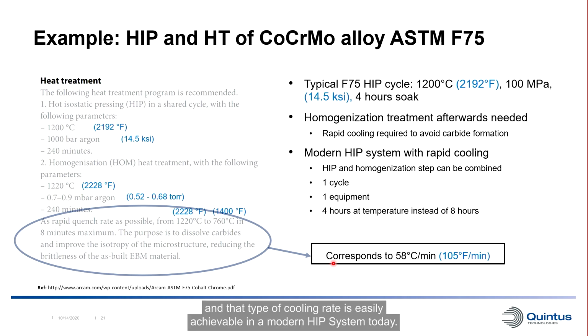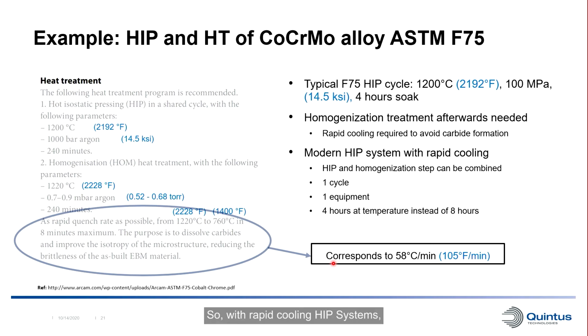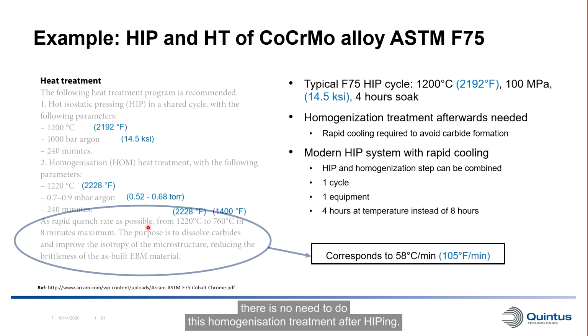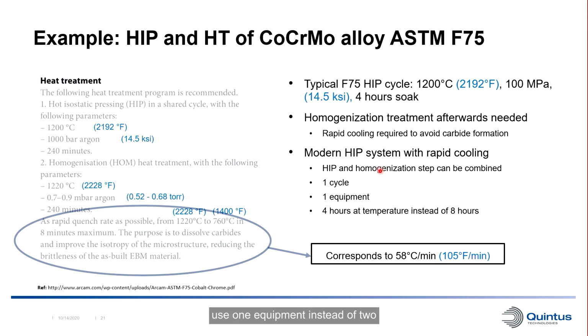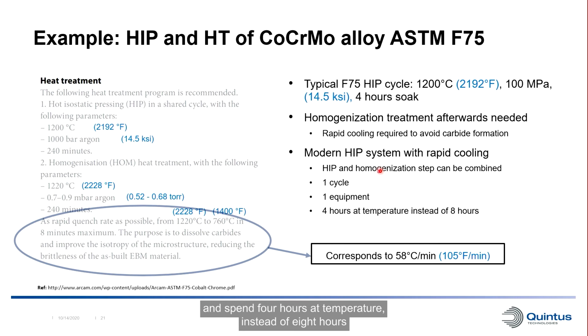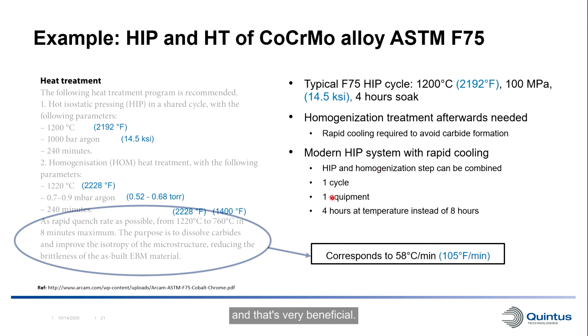And that type of cooling rate is easily achievable in a modern HIP system today. So with rapid cooling HIP systems, there's no need to do this homogenization treatment after HIPping. You can do the HIP step and then do the rapid cooling from here instead. So in that case, you would do 1 cycle instead of 2, use 1 equipment instead of 2, and spend 4 hours at temperature instead of 8 hours, and that's very beneficial.